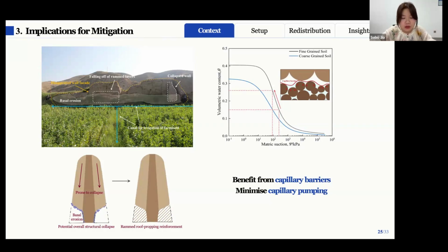However, these repair materials often have different properties from the original soil, leading to poor compatibility. In some cases, they are even much stronger than the original material, which can result in detachment. And the difference in microstructure at the interface can promote salt accumulation, accelerating damage. So the question is, instead of focusing only on strength, can we better control the capillary behavior of the materials? This leads to the idea of applying a capillary barrier system, which is widely used in environmental geotechnics, but rarely considered in heritage conservation.